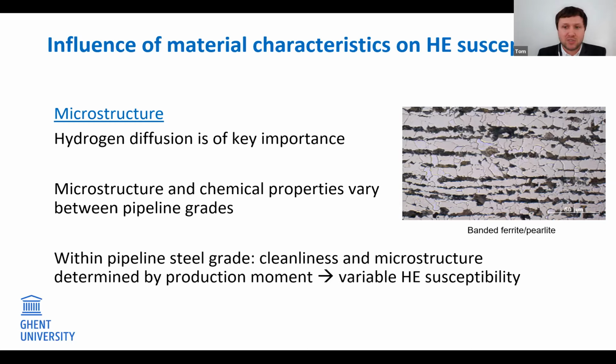The trapping characteristics of these microstructural features will strongly influence the sensitivity to hydrogen embrittlement, as the presence of these traps will affect the kinetics of hydrogen transport, again, the diffusion. For instance, reversible trapping is related to diffusible hydrogen, and this is considered to be the main culprit in hydrogen-assisted degradation phenomena.